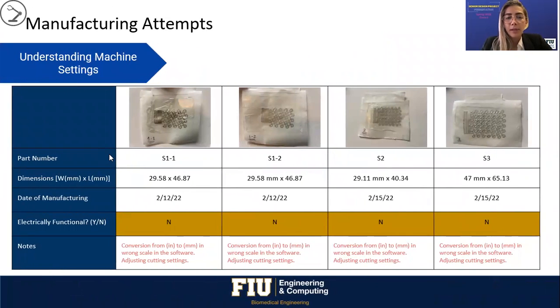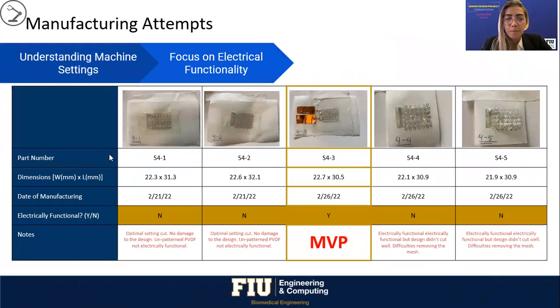We had multiple attempts in cutting the samples and adjusting the settings to obtain the optimal cutting settings for our MVP. So here, the first 2 samples were not electrically functional, but after cleaning the blade, we were able to get a functional sample. Even though we tried to produce more, the mesh was not coming off as smoothly as before and resulted in a broken design.